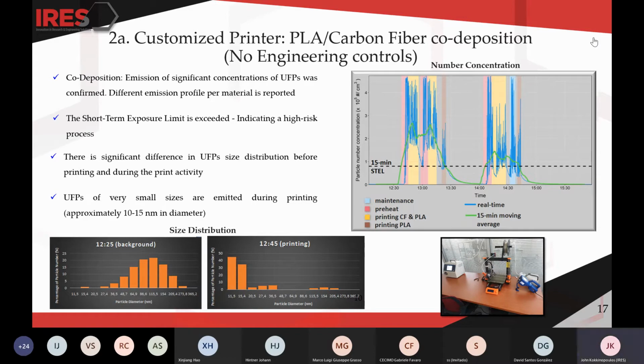Moreover, as you can see on the 2 charts at the bottom, size distribution analysis results indicate that there is a significant difference in the ultrafine particle size distribution before printing and during the print activity. Comparing the ultrafine particle size distribution during printing with that of the background, it can be confirmed that nanoparticles of very small sizes are emitted during printing, approximately 10 to 15 nanometers in diameter. And the concentration of the emitted ultrafine particles is also very high.